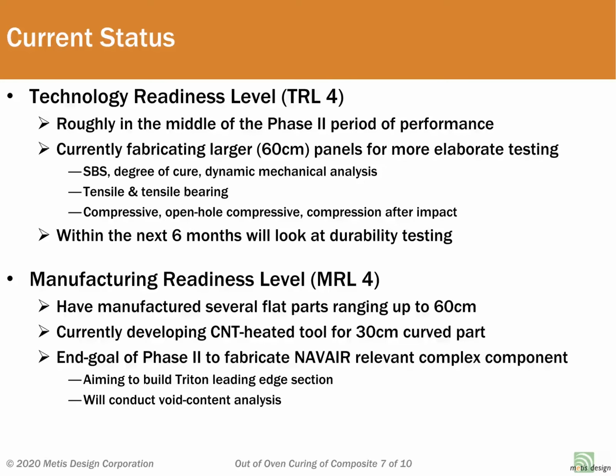In fact, these most recent results actually showed between a 5 and 20% improvement in all properties investigated, including a change to a more favorable failure mode for many of these tests. Our next steps include working with PMA 262 to use this approach to cure a leading edge section of the Triton UAS to demonstrate the process works beyond just flat laminates. Further, we will conduct some durability tests, including for fatigue, delamination toughness, and hot-wet performance.